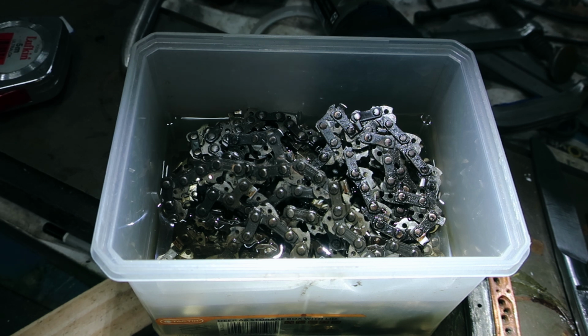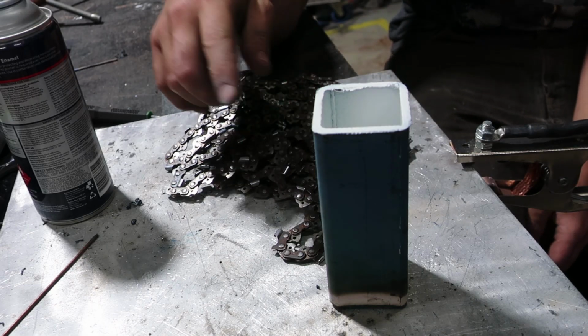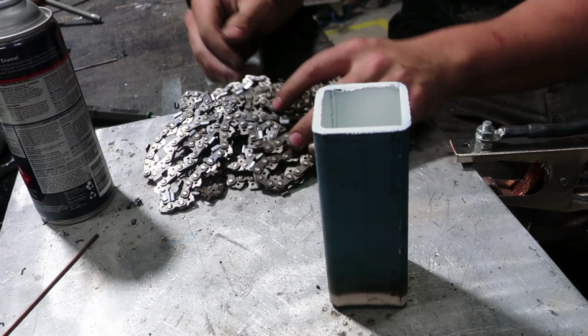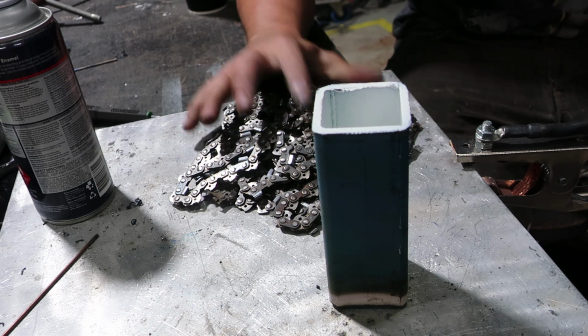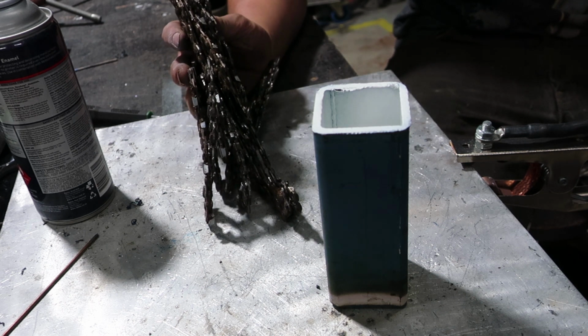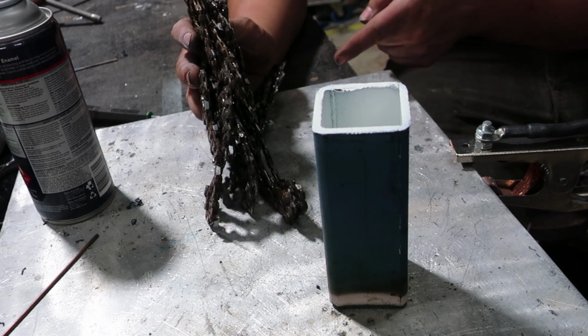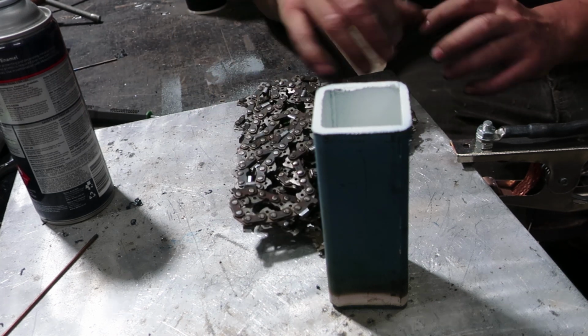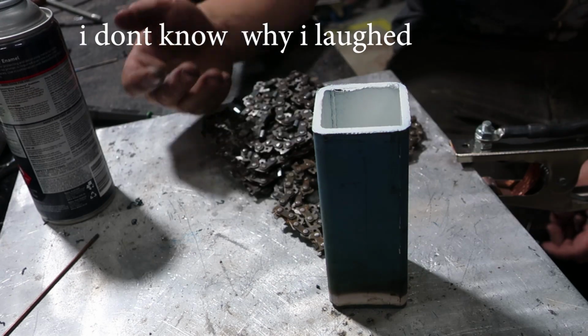Disclaimer: drill a hole. The canister had a gas bubble in it and it ended up splitting, so it all worked out fine, but if you'd rather the canister not split, drill a hole. When I do my canisters, I don't really put a hole in it, allegedly. So what I did here with the chains, after I took it out of the acetone, I lit it on fire just to burn off all the flammable liquid, I guess.